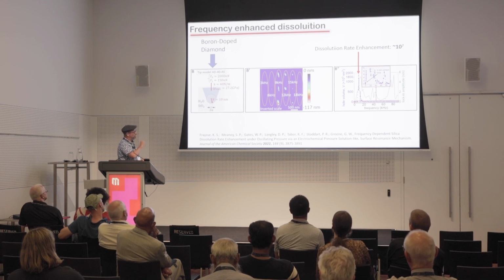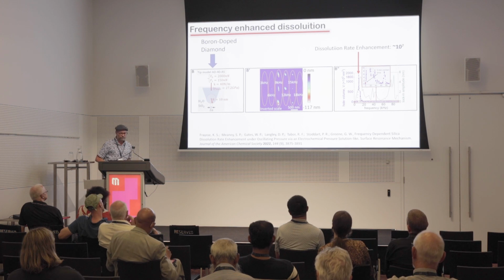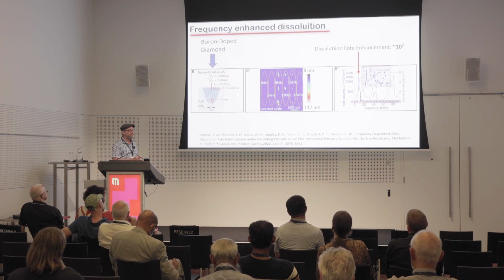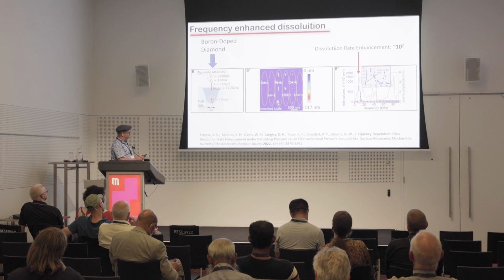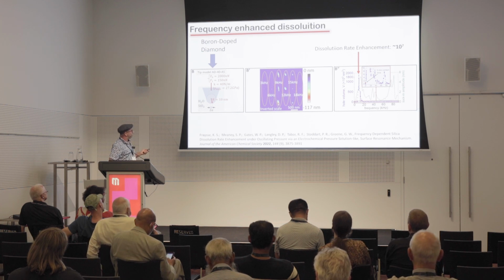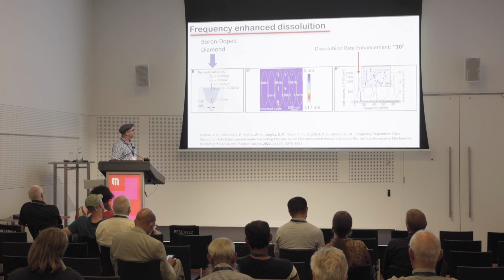So we tried to replicate this result using a process known as force modulation mode. And so what we do is we run the same experiment. This time we press the AFM tip down onto the surface, and over top of that set point force, we apply a sinusoidally oscillating pressure, right?